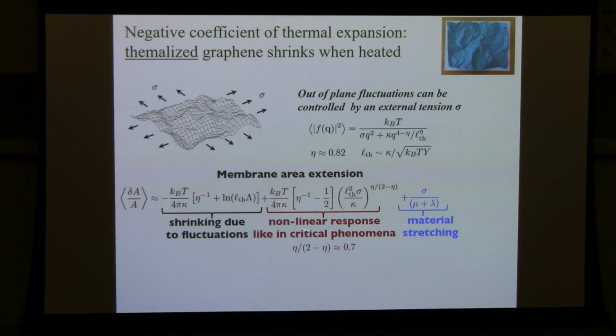This is nonlinear, interesting nonlinear powers of the stress come in here. This is not, like 3. This power is some fractional thing that depends on this exponent eta. In any event, if you take away the external stress and just look at the shrinkage due to thermal fluctuations, we can calculate that fairly accurately in terms of, this is like a 1 over a lattice constant. Here's the thermal length. And then what comes out in front is a negative number. So what that's basically saying is that as I change temperature, the thing shrinks. It's shrinking for entropic reasons.